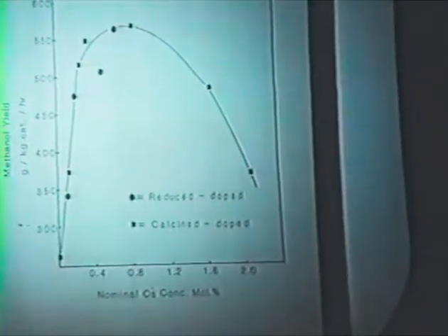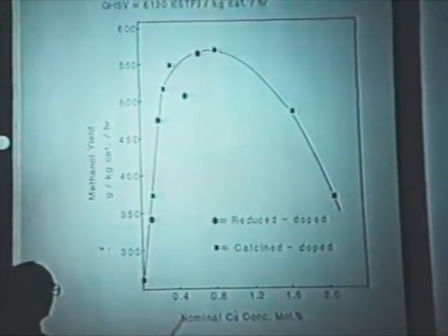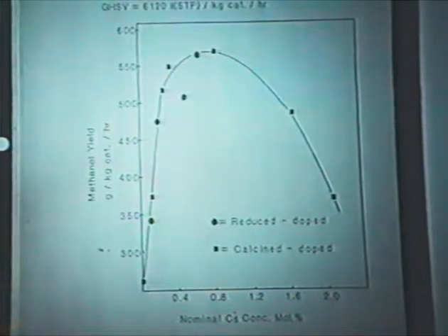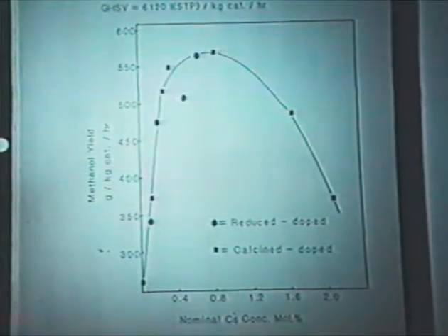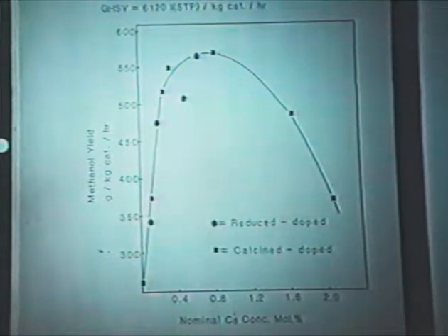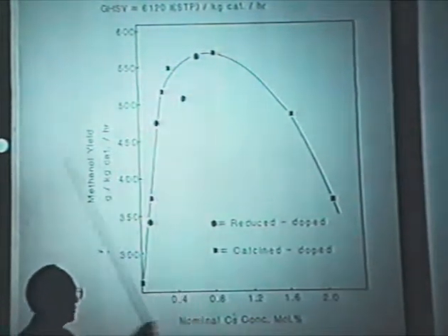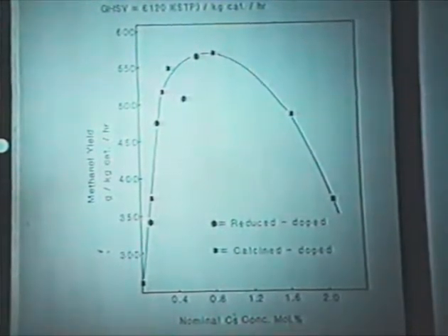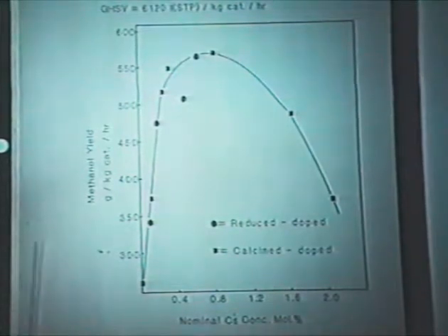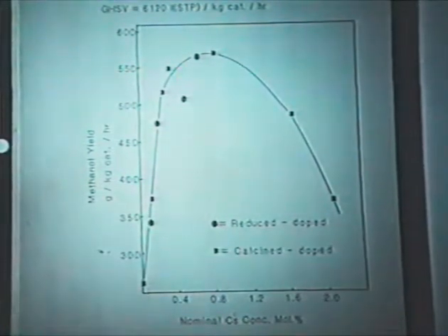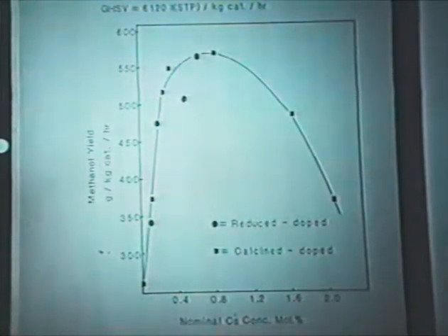You'll note this is a low doping level, whereas before with the MoS2 we were using 10 to 20 weight percent of the alkali dopant at an optimum concentration. So again, we've used the cesium-promoted catalyst. This is our best catalyst. And again, we see that we see a maximum in the cesium doping level on the activity. This indicates that this catalyst is a bifunctional catalyst. If we put on cesium, we would say that it activates CO. If we put on too much cesium, it's covering up the hydrogenation function of the catalyst. So again, we're using typically about 0.4 weight percent doping level because the ester generation is lower. As we increase the doping level to 0.8, which is good, we get more ester formation, however. So we tend to stay at 0.4 weight percent.